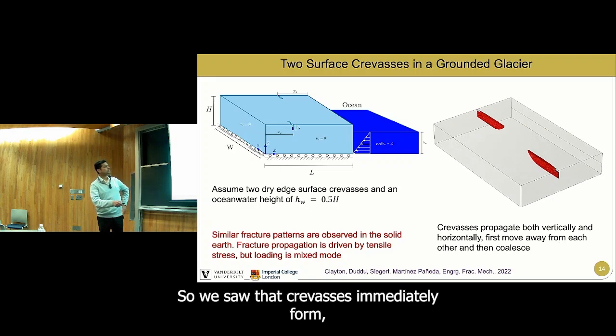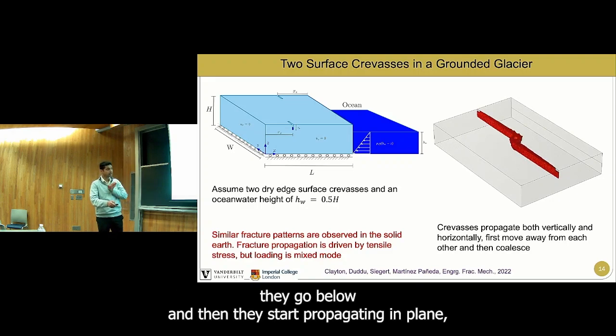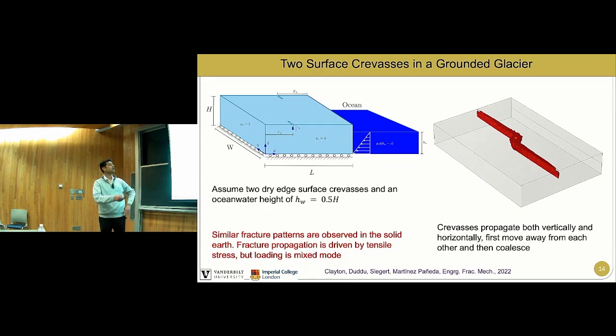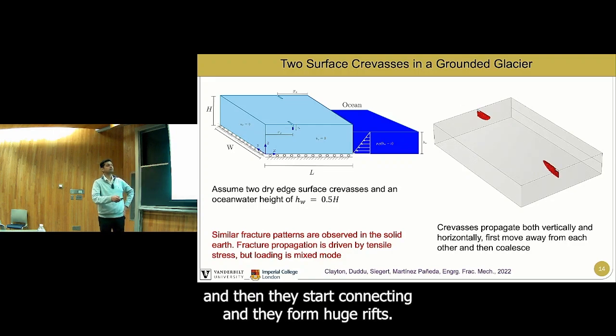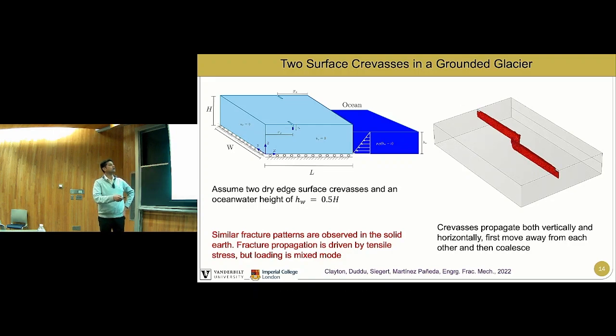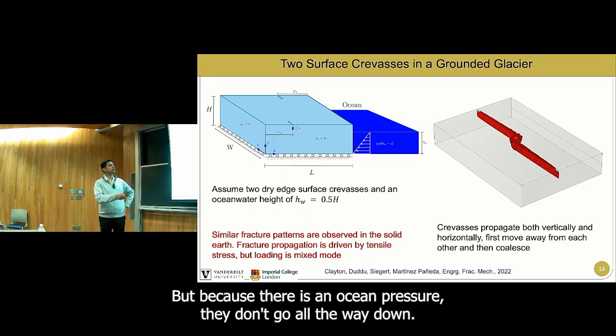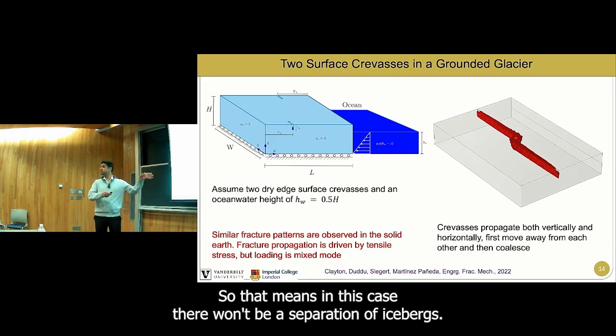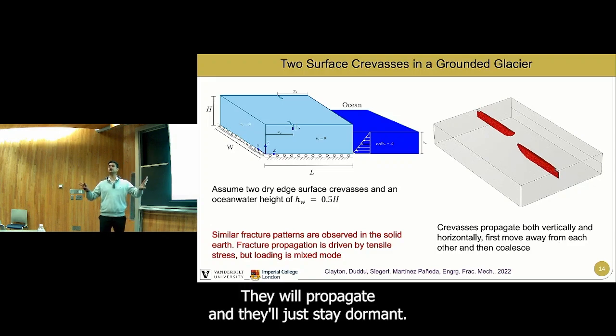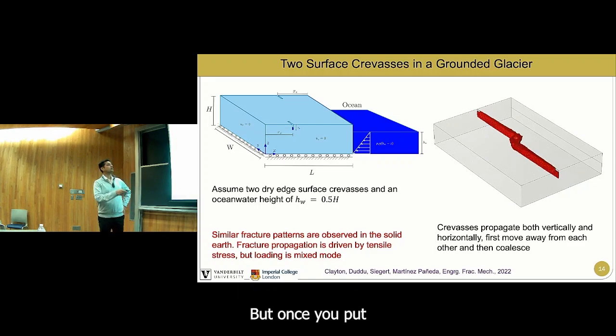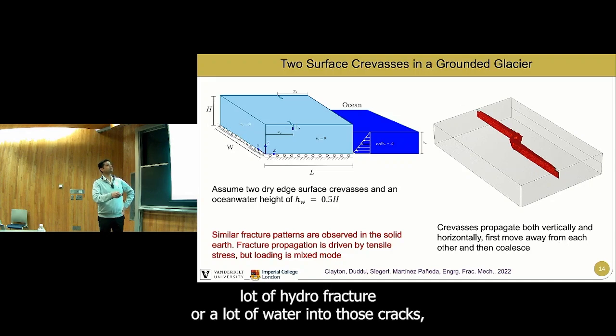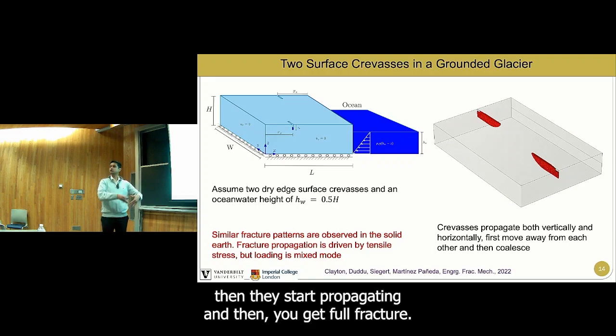Yeah, so we saw that crevasses immediately form, they go below, and then they start propagating in plane. And then they start connecting, and they form huge rifts. But because there is the ocean pressure, they don't go all the way down. So that means in this case, there won't be a separation of icebergs. They'll propagate, and they'll just stay dormant. But once you put a lot of hydrofracture, a lot of water into those cracks, then they start propagating, and then you get full fracture.